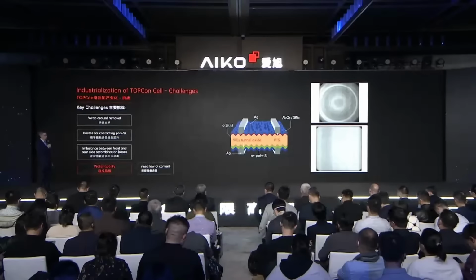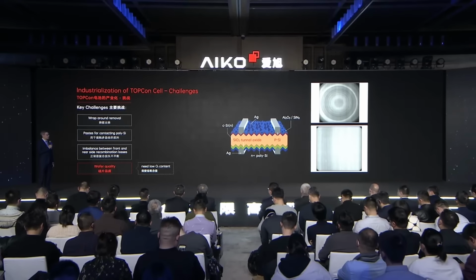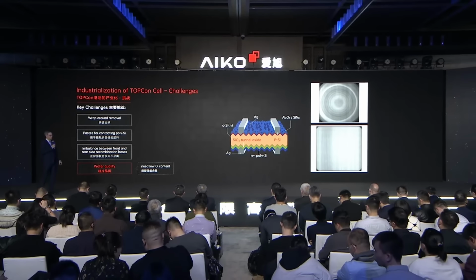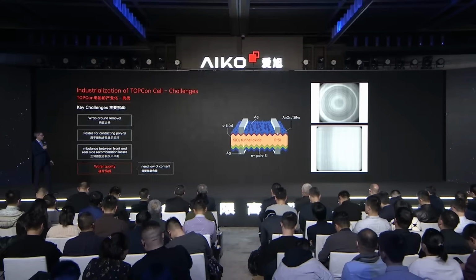And another important aspect, which has also been mentioned beforehand, is the wafer quality. So boron diffusion typically takes place at 1000 degrees centigrade, and then this can lead to quite fast formation of oxygen rings, as you see here in the upper PL image. And an important step towards wafers free of oxygen rings was to process wafers with a very low interstitial oxygen content in the order of 10 ppm.